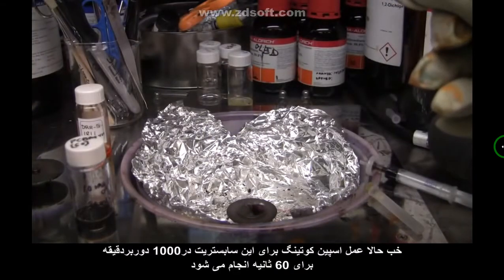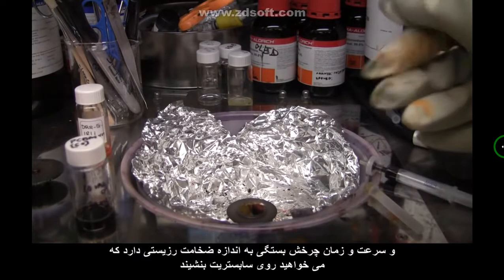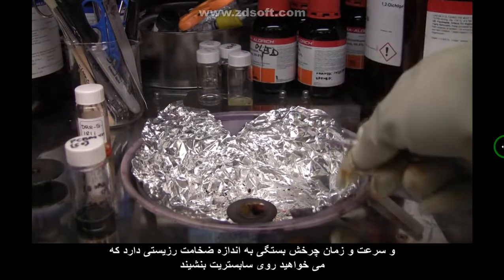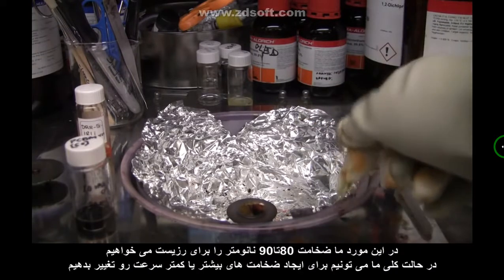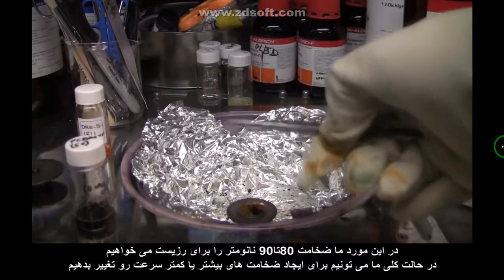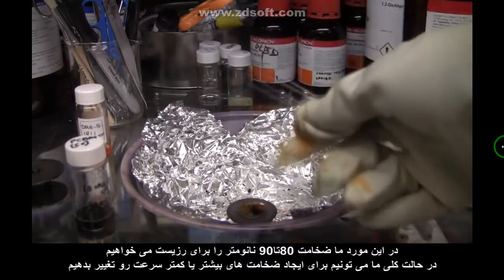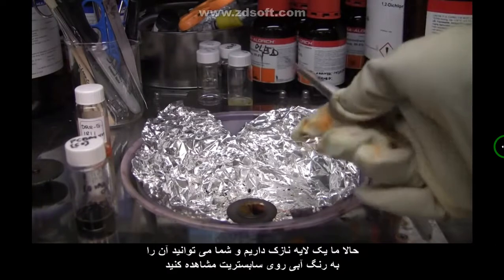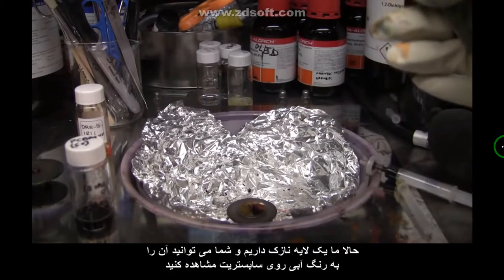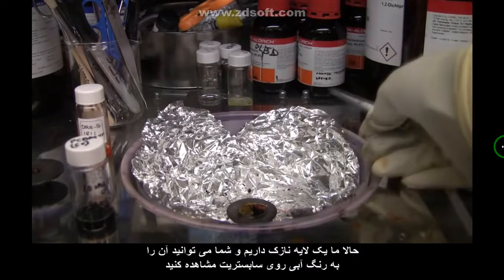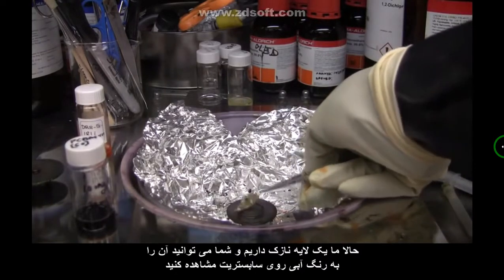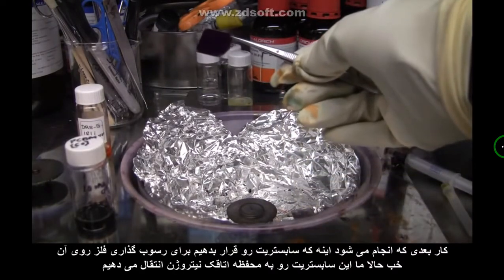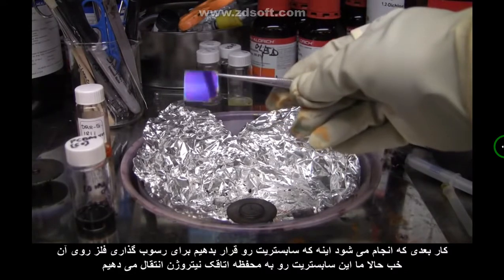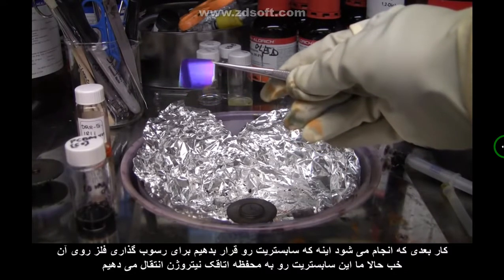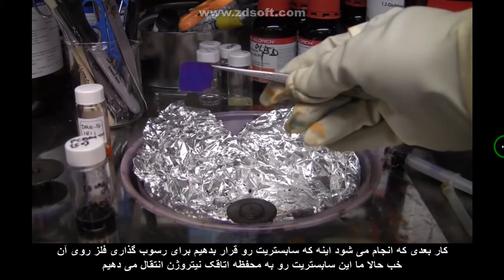Right now we are spin coating this semiconductor at 1000 RPM for 60 seconds, and the speed and time depend on what kind of thickness you want. In this case we have around 80 to 90 nanometer of PCBM, but generally we can change the speed to get thicker or thinner films. So now we have a nice film on this. You could see the slightly blue color of the PCBM film on this substrate. The next thing will be to place these substrates for metal deposition. So we'll transfer these substrates through our antechamber to the next nitrogen glove box.